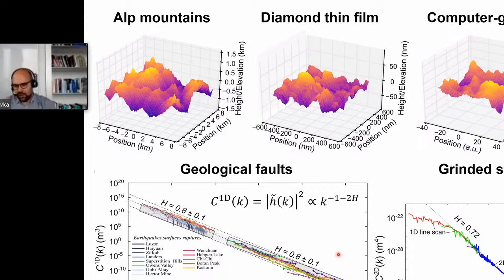The right plot is taken from one of Bouchaud's papers on a steel surface, and you see that even if you look at smaller scales, in this case steel, you often find the self-affine scaling properties here down to measurements of the STM. Hurst exponent, so the value of these scaling exponents are often between 0.7 and 0.8.